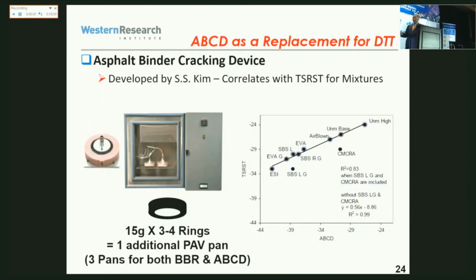So we looked at the early Superpave specifications, where there was the direct tension test. That was to address polymer modified asphalt. For some reason it has not been developed as much, and there are issues with reproducibility and robustness. So we tried to find a surrogate for that, and the most available one we found is the ABCD test. I guess you're familiar with this test. It's kind of like the TSRST on binders. It was developed by Sang-Soo Kim a long time ago, and he did some studies showing good ranking for polymer modified asphalt. So we proposed to use this test in the new specs, but it's just a proposition at the moment.